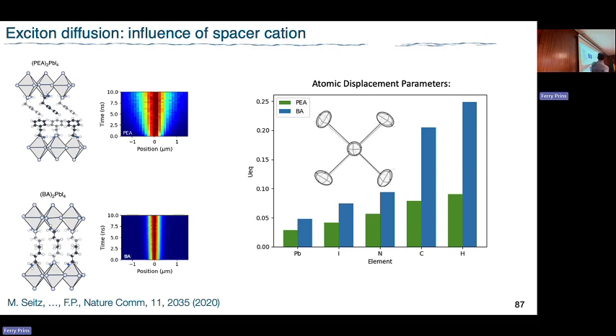You can see this when you compare phenethylammonium and butylammonium, looking at the octahedra unit cell, but actually you can look at all of them, where butylammonium always has a much larger error bar than phenethylammonium. So this atomic displacement parameter is now a measure of how floppy my perovskite is. They're very soft semiconductors compared to silicon, things can move, they're ionic. So apparently phenethylammonium is much more rigid than butylammonium.